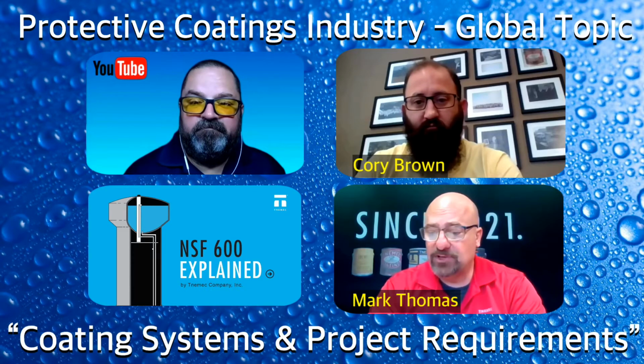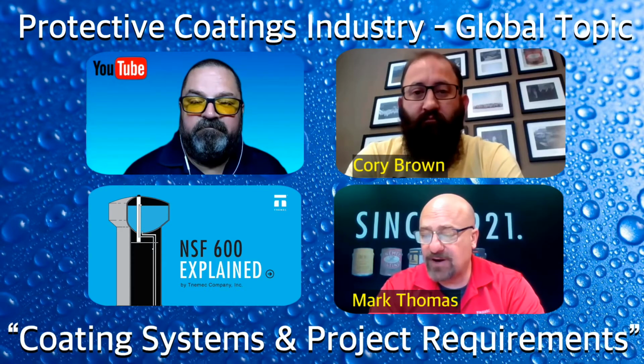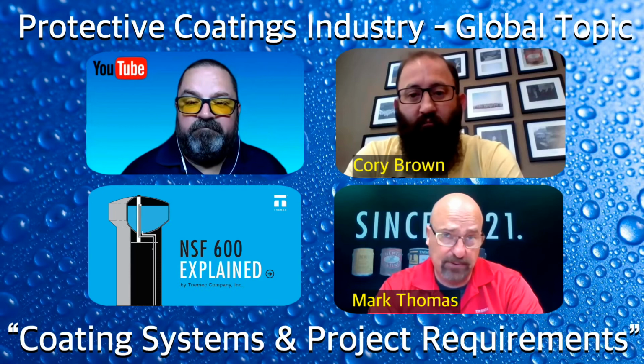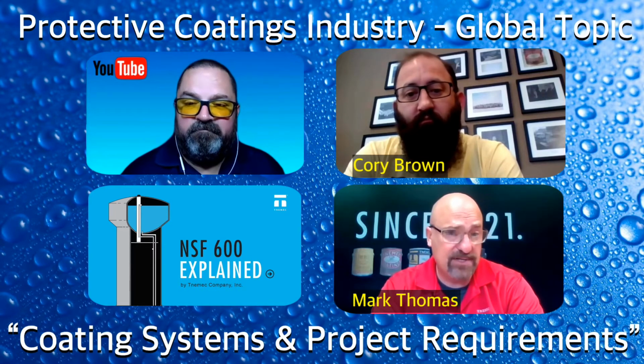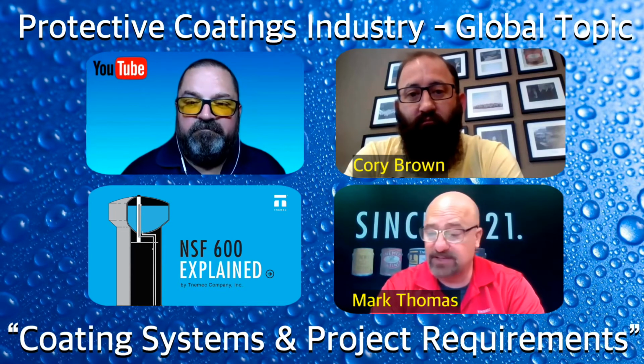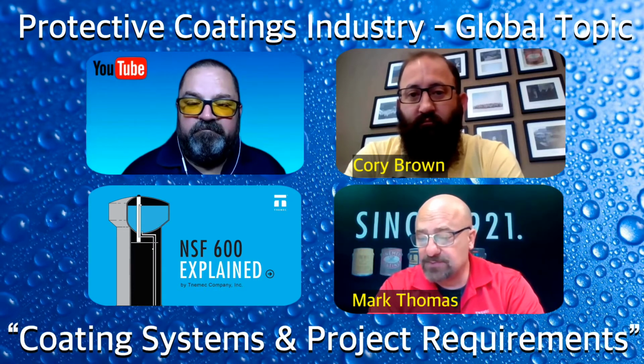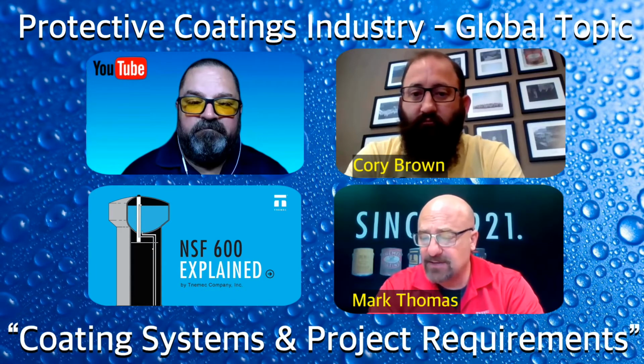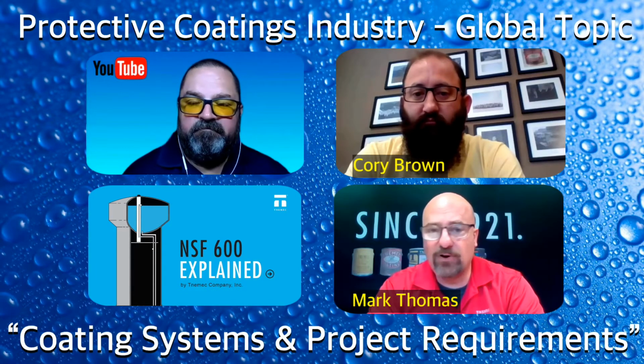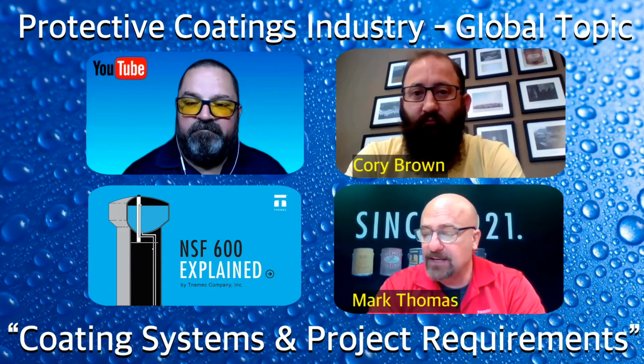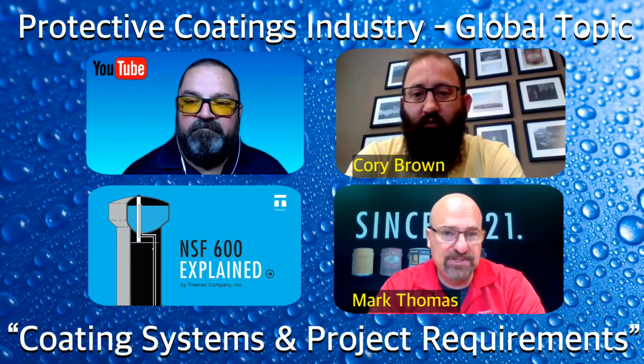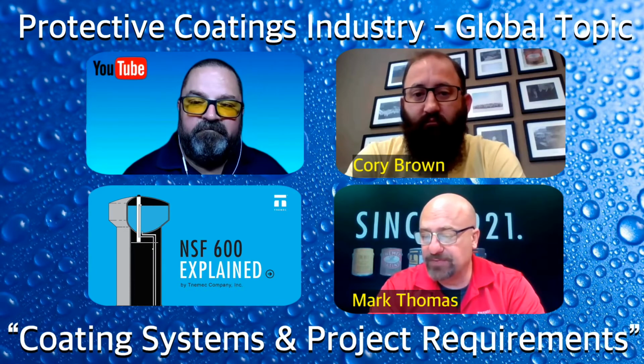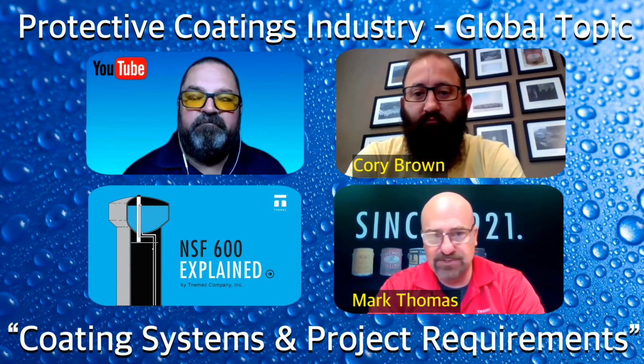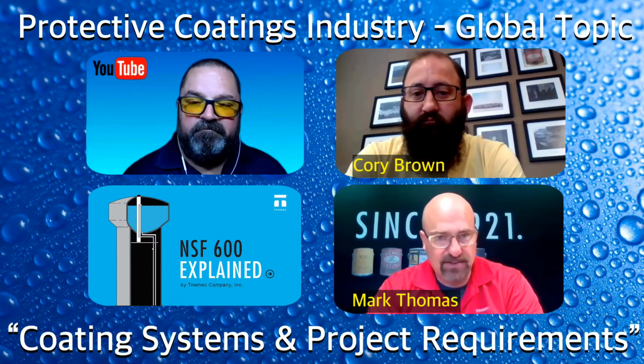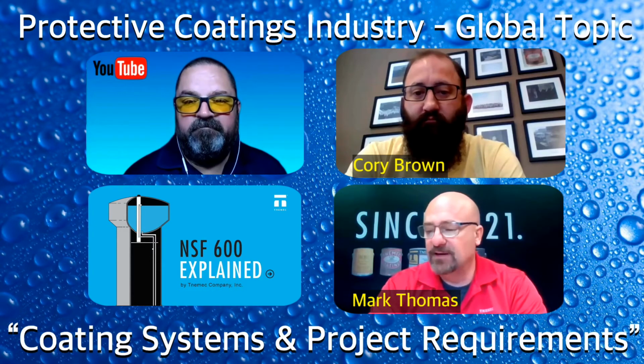You also want to look at a humidity test called ASTM D4585. That would be applicable to a coating that's above the water line in a water tank, say, but in extremely humid conditions. Tnemec generally runs those tests out to about 2,000 hours as a minimum. And then there's 2 corrosion tests that we feel are really good indicators of overall coating performance and durability. And that would be B117, which is a salt fog test that a lot of engineers are familiar with. That's been out there for a long time. There's a huge depth of data with older technologies that you compare apples to apples with newer technologies.